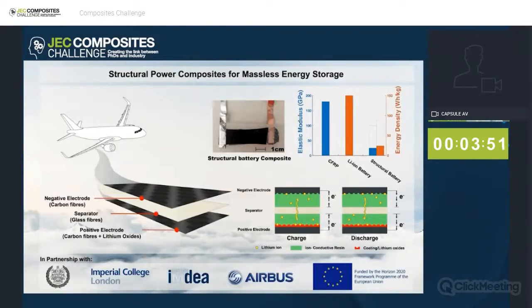As multifunctional materials, structural batteries are mechanically robust, strong, and so they can serve as structural components. But they can also store energy, electricity, or electrochemical energy, if you prefer. They are also laminate composite materials, so they include several layers. They include carbon fiber-based electrodes, an anode that is just bare carbon fibers, and a cathode where the carbon fibers support lithium oxide particles. You may find in between some glass fabric that prevents contact between the electrodes.